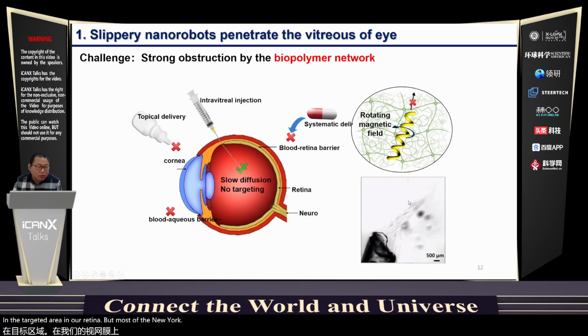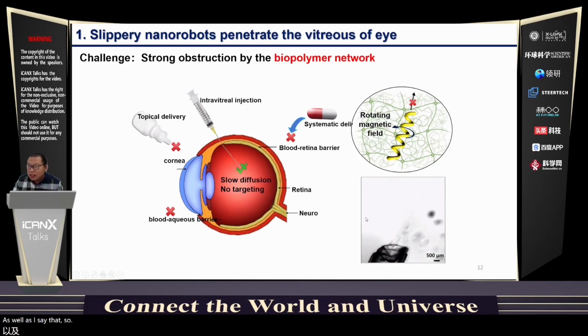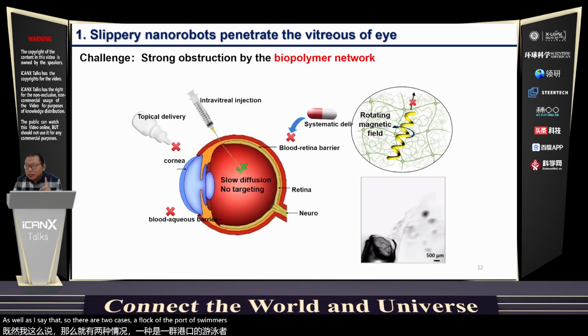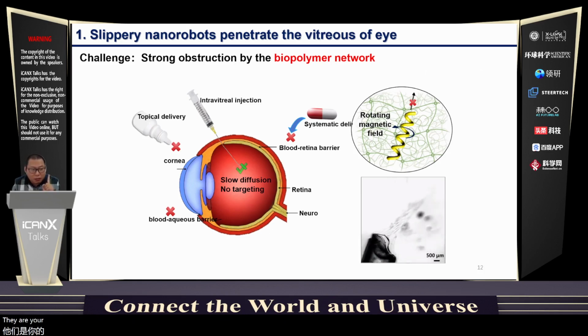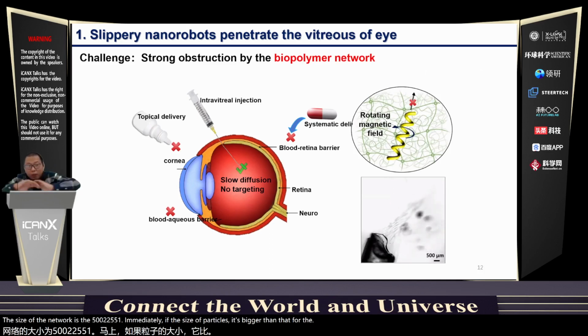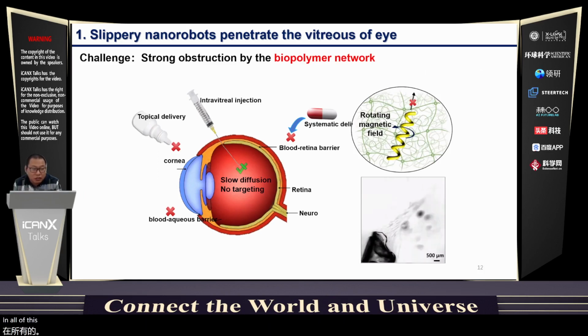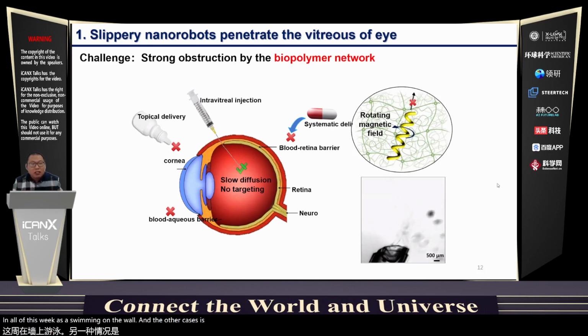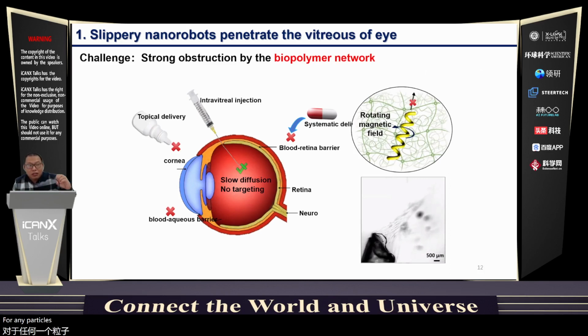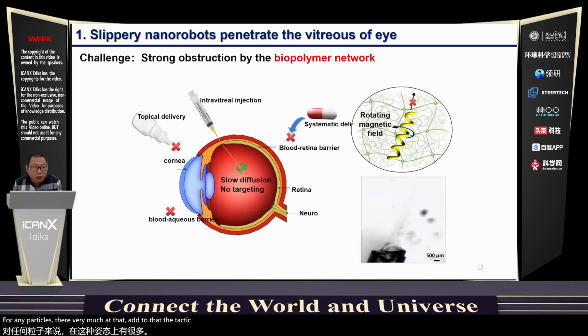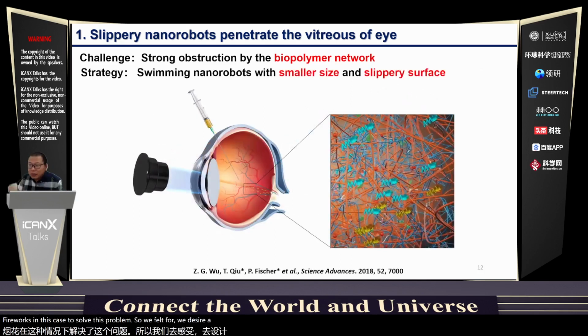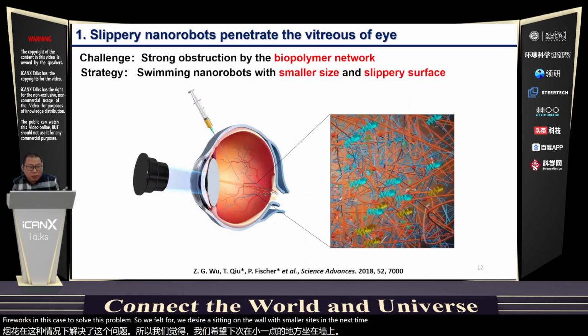But most of the work has failed because, as I said, there are two cases that block the propulsion of the swimmers. The first one is the biological network. The size of the network mesh is 520 to 550 nanometers. If the size of the particles is bigger than that, the spatial block will prevent the propulsion of the swimming nanorobot. The other case is that the building blocks made of type 2 collagen are very adhesive, so any particles are very likely to attach to the type 2 collagen fibers. To solve this problem, we designed a swimming nano robot with a smaller size than the mesh size, with a small size and slippery surface.